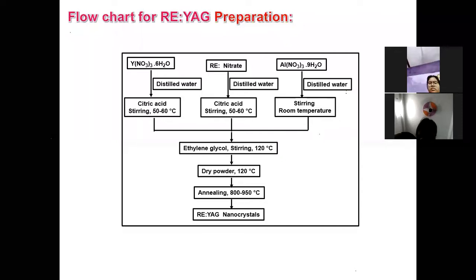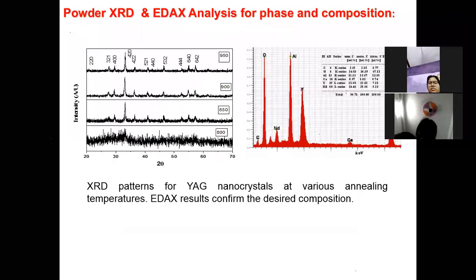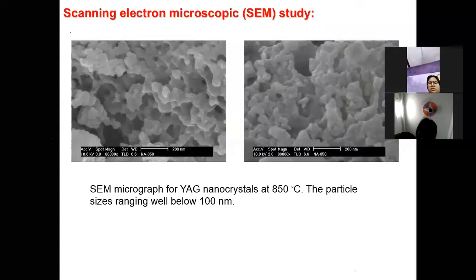So this is basically the flow diagram of how we finally end up with the nanocrystals of Re doped YAG, and that can be used for making composite discs or rods and make the laser out of it. So again, to characterize those materials, what has been made, you use XRD, you use EDAX to see whether the material is of the same quality, same concentration, or same basic structure.